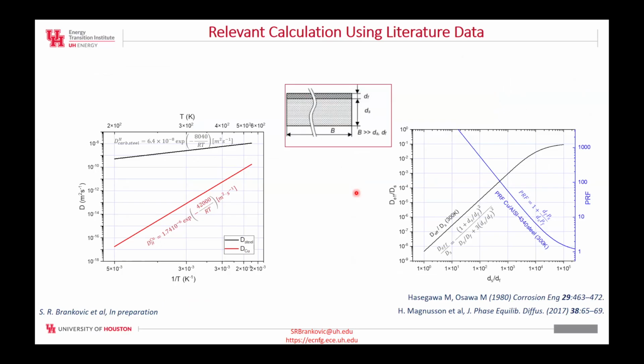So you can see that the hydrogen diffusivity in copper is of order at least 3 to 4 orders of magnitude lower than in steel, which is important. But also you can calculate permeation factors for, let's say, copper barrier layer here on 4340 steel at 300 Kelvin, which is room temperature. And you can see that if you put 1,000 times smaller thickness of the barrier than it's a wall of the steel, then you can reach the permeation reduction factors of about 100. In roughly engineering language, that means that you will probably reduce the potential of hydrogen embrittlement about 100 times.